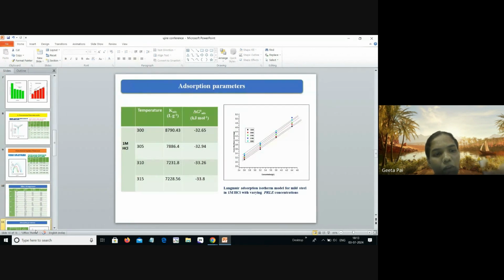Then it can be confirmed by the adsorption isotherm. In the literature review, if we get the delta G value of -20 or less than -20, the inhibitor molecule adsorbed to the metal surface is held by weak van der Waals forces. If it lies between -20 to -40, then the inhibitor molecule is bound to the metal surface by strong chemical bonds. In the present work, I got values of -32 to -33.8. It indicates that the effective component present in the plant extract will bond to the metal surface by strong chemical bonds, and the inhibitor will hold good to the Langmuir adsorption model.